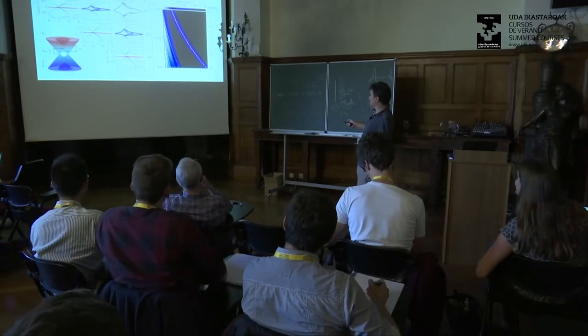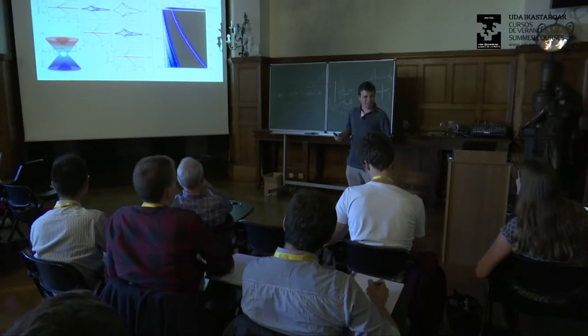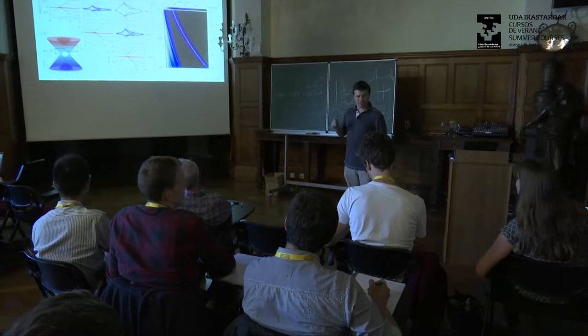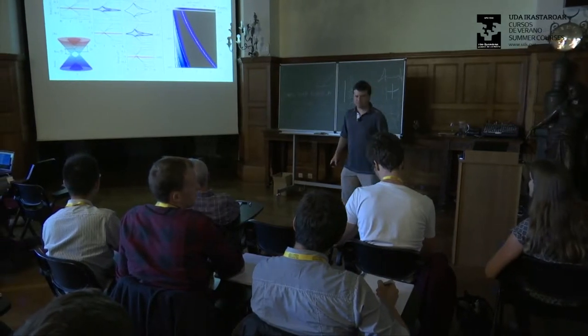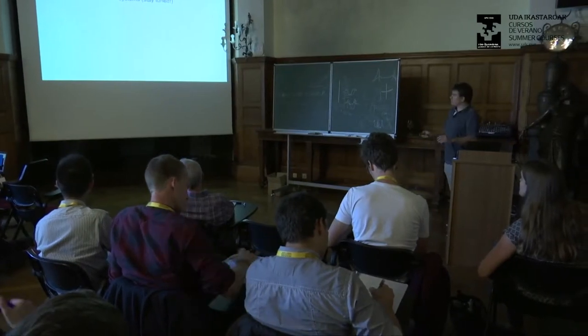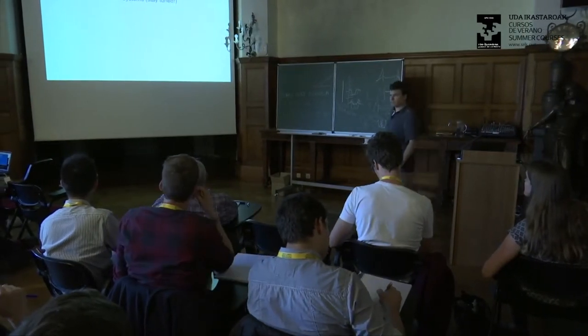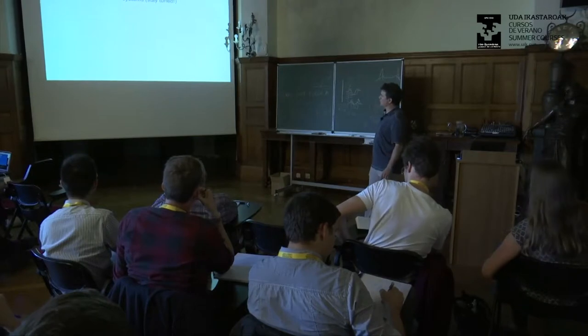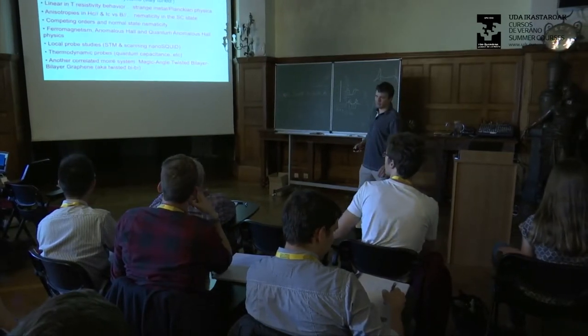But for 3 degrees, you see, you have to apply 30 gigapascal. There are techniques to apply such pressures, but not in their apparatus. Yeah. So, in addition to this, which was the first reproduction of an extension of our results, a lot more has happened since then.